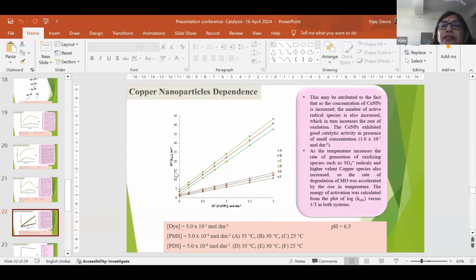And here we see the effect of temperature: if the temperature increases, the rate of generation of oxidizing species such as sulfate radicals and higher valent copper species also increases. So the rate of degradation of methyl orange was accelerated by the rise in temperature.